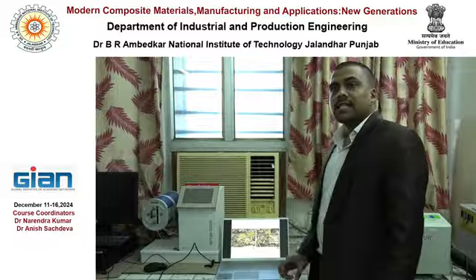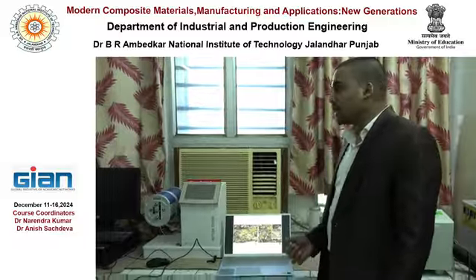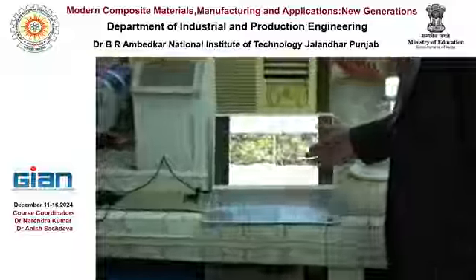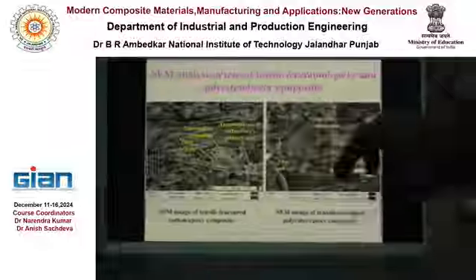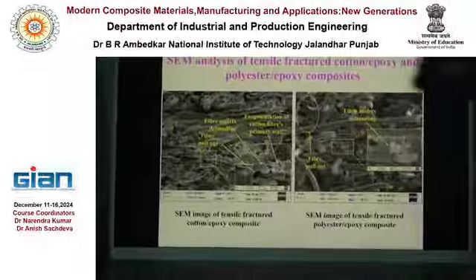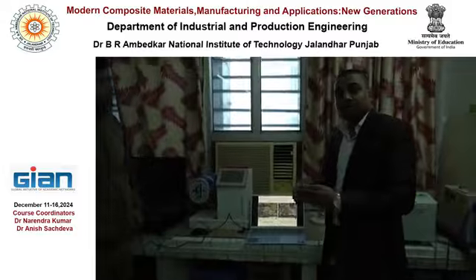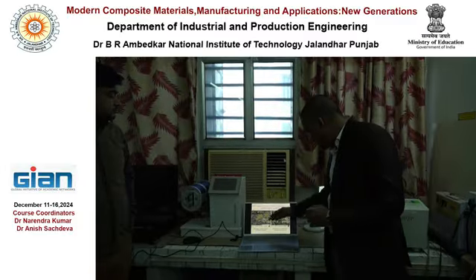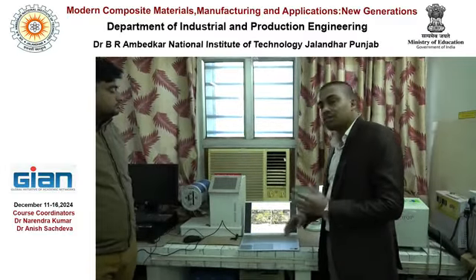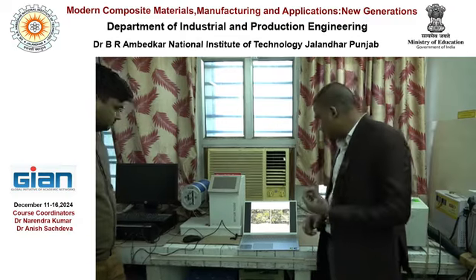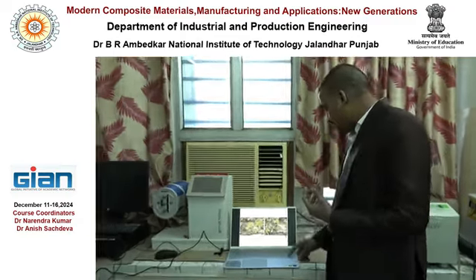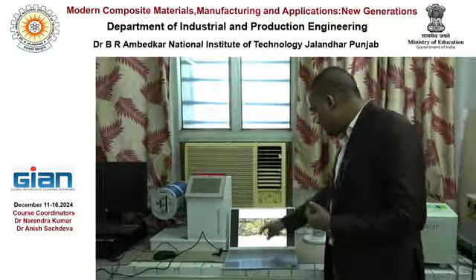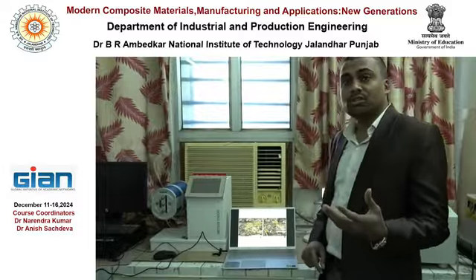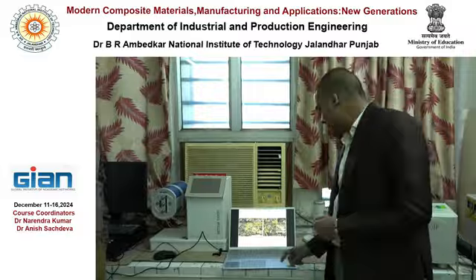This is the same image. Again, you must be aware of the scanning electron microscopy of the fractured specimens. We try to understand how effective the fiber matrix interface is, and you can find out how your fibers are actually fractured in the composite material, whether there is any fiber matrix debonding or fiber pull out. So fiber pull out is an indication of poor fiber matrix interface.